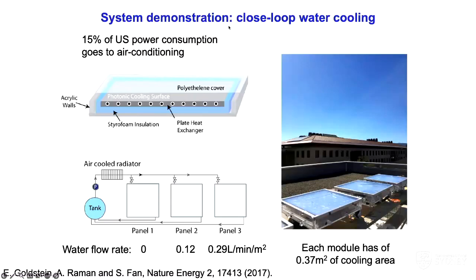This cooled water can then be used in a water-based cooling tower in a standard air conditioning system, and the reduced water temperature of a few degrees translates into a 10 to 15% improvement in the system efficiency. 15% of US power consumption goes to air conditioning. So a way to systematically improve air conditioning system efficiency can therefore be potentially important commercially.